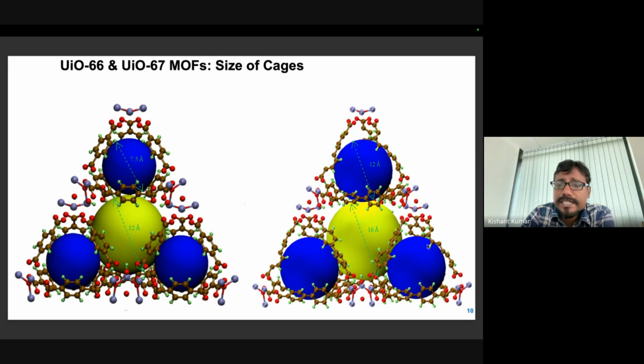Here you can see this is UIO 67, where the metal cluster, the inorganic cluster, still remains the same, but you can see the organic linker is made up of two benzene rings instead of one. You can see over here, it has two benzene rings. That's why you see larger pores: compared to this 12 angstrom, here you have 16 angstrom. Here you have a secondary pore, that is 7.5 angstrom. Here you have 12 angstrom.